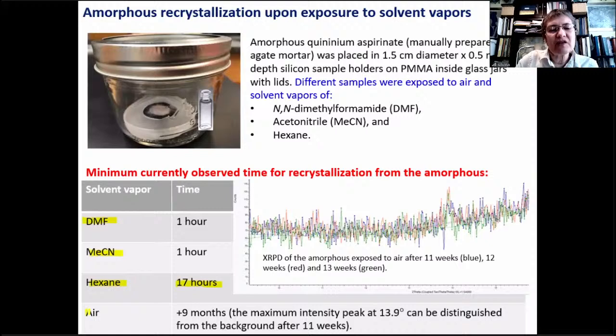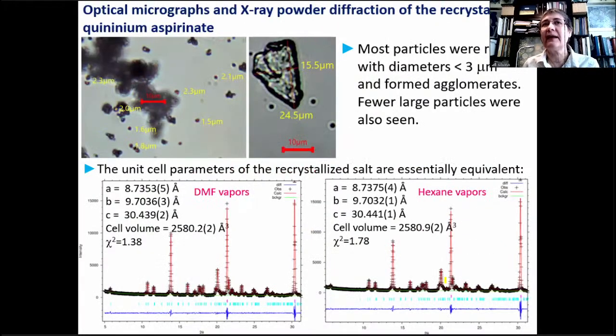But if the amorphous is kept under air, it can stay more than 9 months. And the only thing that is seen is the maximum of the diffraction data of the crystalline product showing up there a few weeks after it has been left under air. So then definitely these solvent vapors really accelerate the recrystallization of the amorphous. And what is observed is the crystalline product obtained by mechanochemistry when liquid additives are used. So the unit cell parameters of the recrystallized salt are essentially the same if dimethylformamide vapor or hexane vapor is used. So we can see that they are within the experimental error for the laboratory X-ray powder diffraction that was used for their determination.